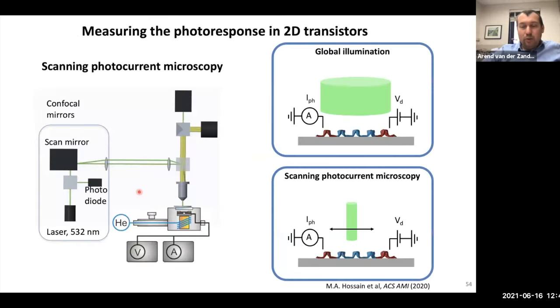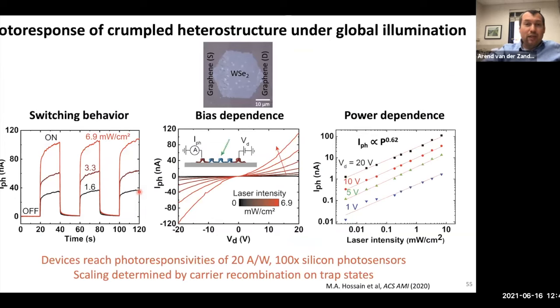And so what we can do is shine a laser on it and see how well it works as a photodetector. Here we have another one of these devices, again graphene electrodes and the 2D material in between. Here we have conductivity versus time. We start with the light off and you can see that there's no conductivity. Then we shine light on it and it turns on. It's detecting the light. Hey, it works. Turn it off and on and off and on, and you can see the current through the device switching on and off.